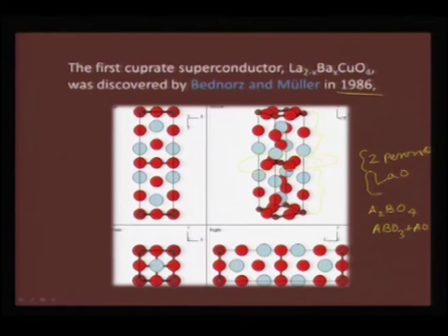So, this forms your K2NiF4 structure, and as you would see here, this is one unit cell, and in this unit cell you have copper in the AB basal plane, and it is not along the C axis, and this is the AB plane interaction which makes this a superconducting compound.